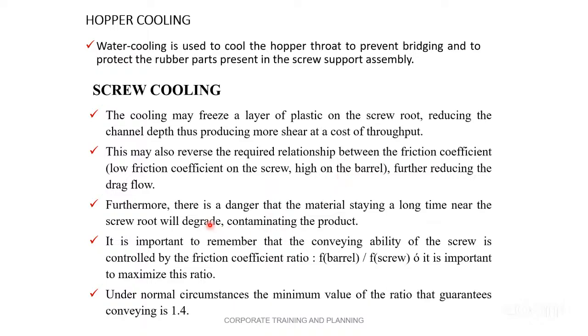Again, there is a danger that the material staying a long time near the screw root will degrade and contaminate the product. Yes. We have to heat the screw. Otherwise, what will happen? The material starts to degrade at the root of the screw, and that will contaminate the product.